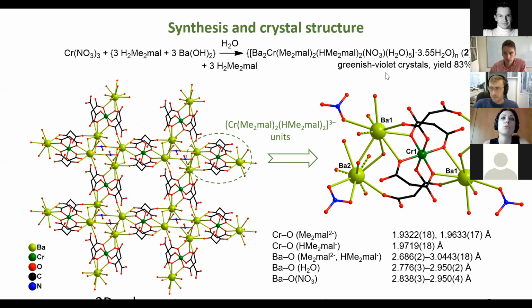A similar reaction with an excess of dimethyl malonic acid led to formation of the two-dimensional polymeric compound constructed from mononuclear anionic units, in which the chromium atom is coordinated by two malonate dianions in chelate mode and two monoprotonated malonate anions in a monodentate mode. Barium atoms are linked to each other by bridging water molecules and by nitrate anions. The coordination environment of barium atoms is completed with free water molecules.